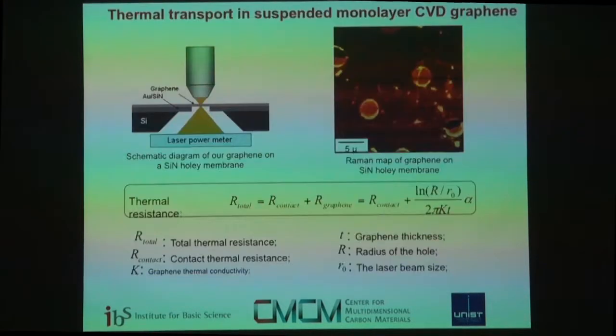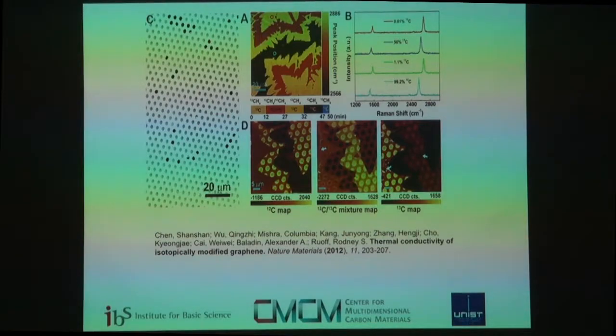Now, the way that's done is, I don't have a picture, but you first have to measure the shift, for example, in the 2D peak as a function of temperature. So you have a home-built cell where you put your graphene samples in, and then you change the temperature, and you look at the shift in either the G band or the 2D. Better to use the 2D because then you have a slightly smaller error because there's a bigger shift for a given temperature change than the G band.